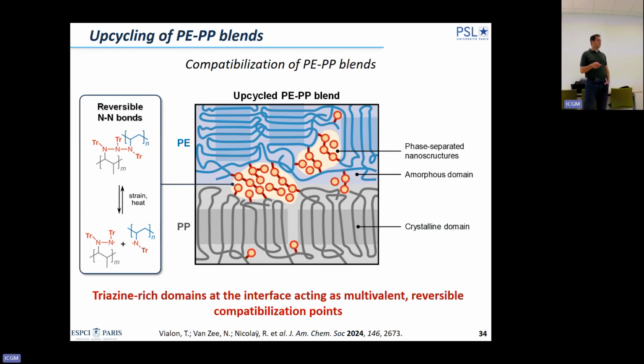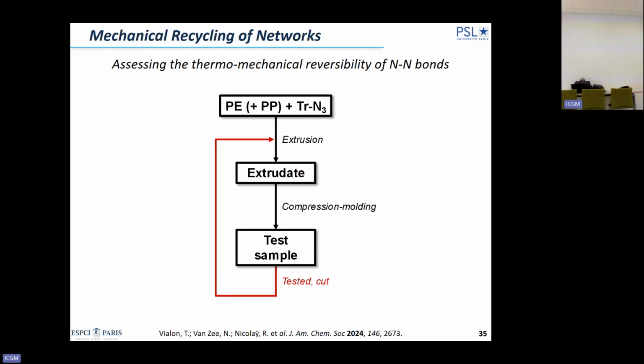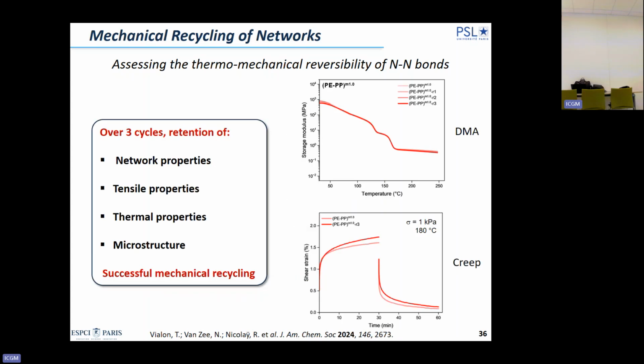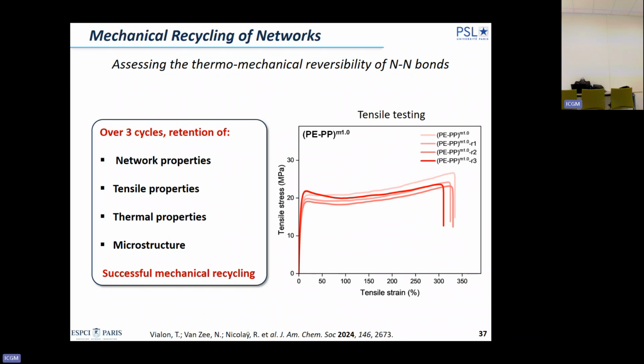And this material is recyclable. Once you have made it by reactive processing, you can take the sample and reprocess it without undergoing reactive extrusion. You can just reprocess it, and you will have the same properties. You preserve all the properties. You preserve the tensile properties. You preserve the creep resistance, and you preserve the phase separation.